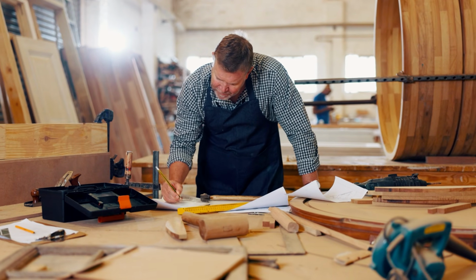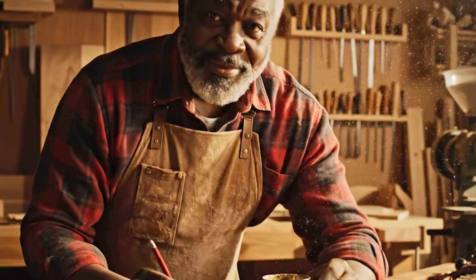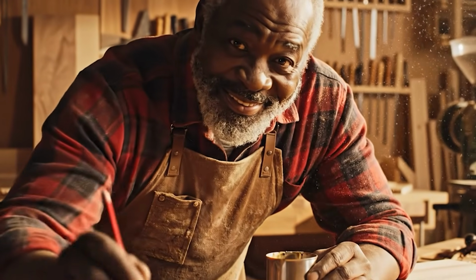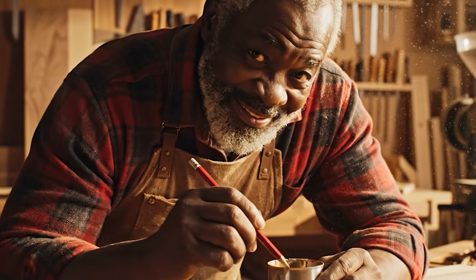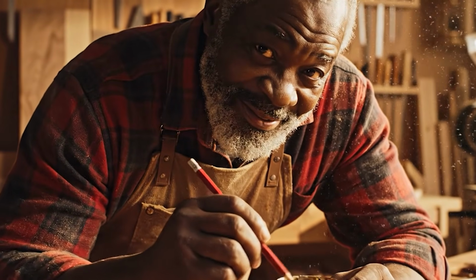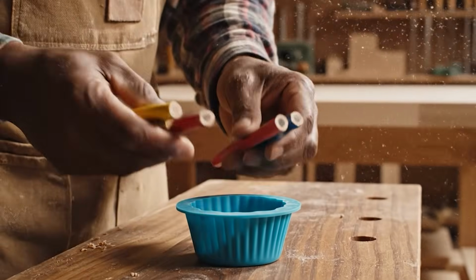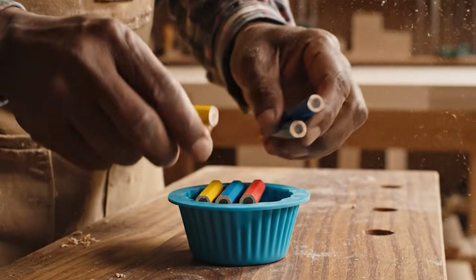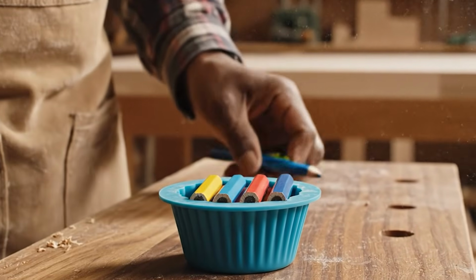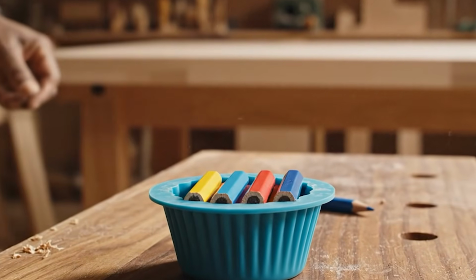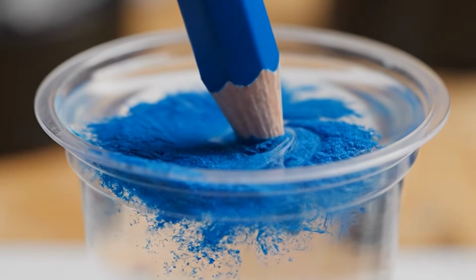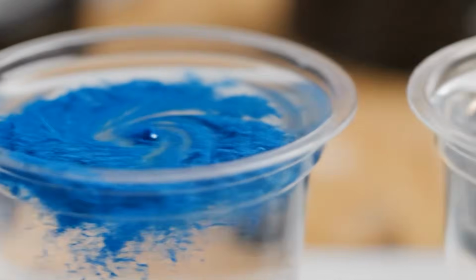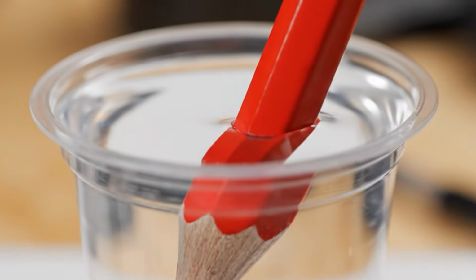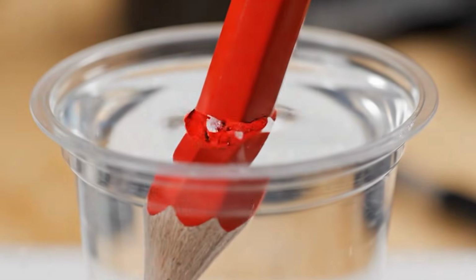Now, for that bonus tip I promised at the beginning, here's something that'll save you real money and real heartache. Before you commit to your full pour, always do a test pour in a small disposable cup using the same epoxy, the same pencils, and the same conditions. Cut a few pencil segments, stand them in a little silicone mold or a paper cup lined with packing tape, mix up a small batch of epoxy, and pour it.